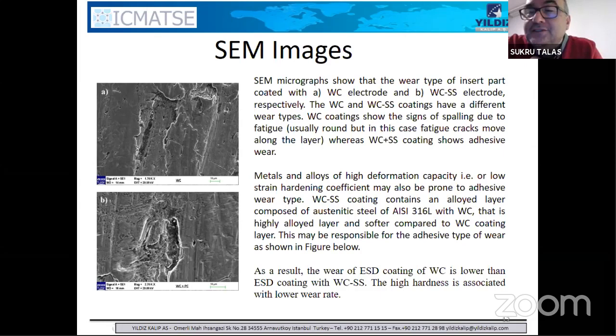So that's the advantage. With hardening, as soon as that worn place appears and is obvious, you have to weld it or hard surface it, then grind it. But in this method, you don't have to grind as well. You can do ESD coating on top of this coating layer. So there's an advantage to this method.